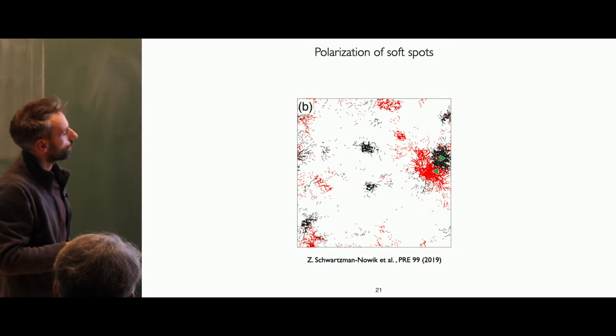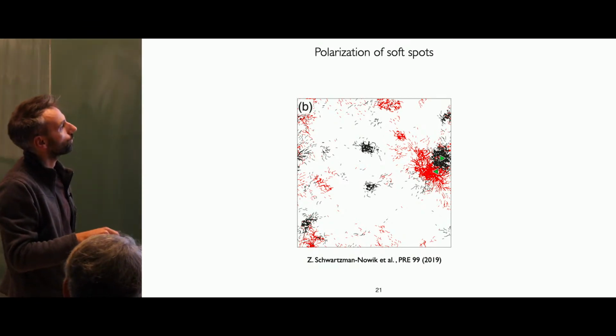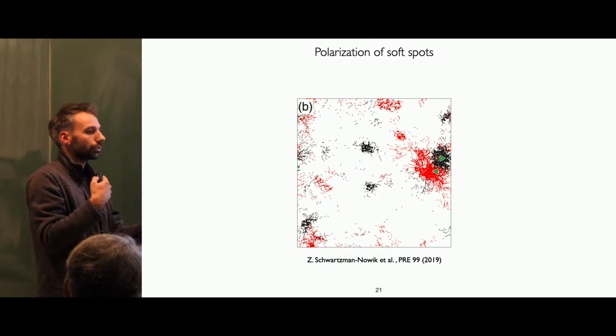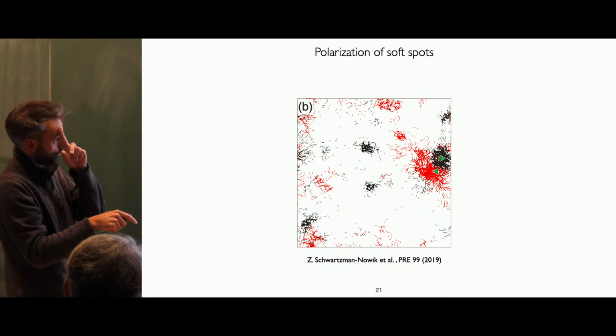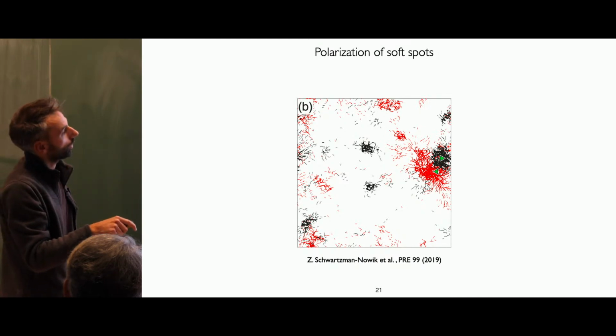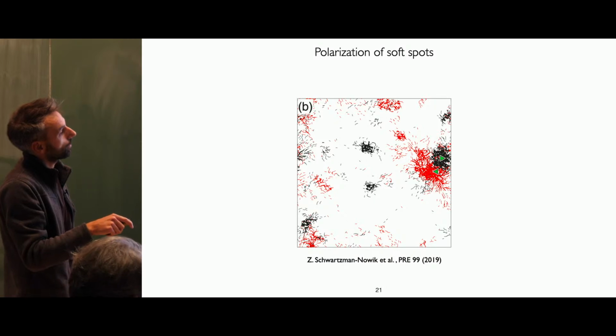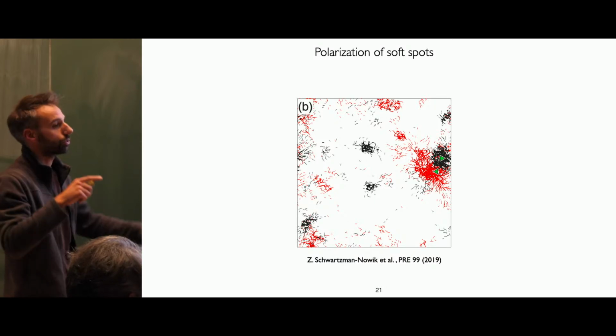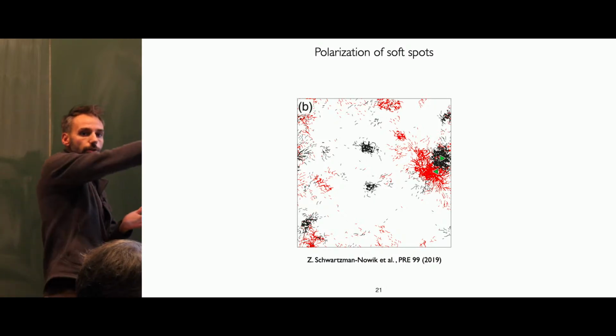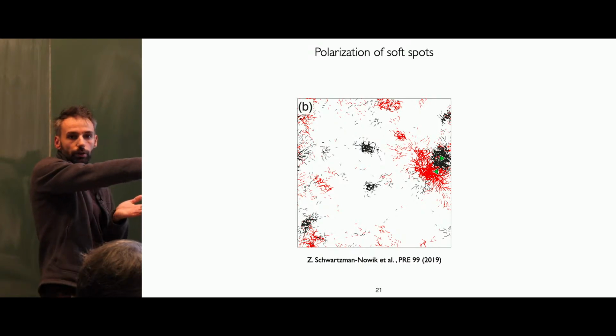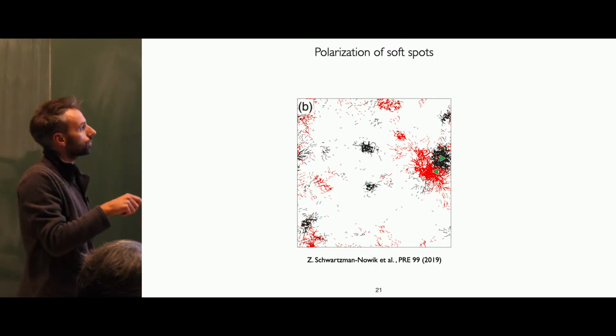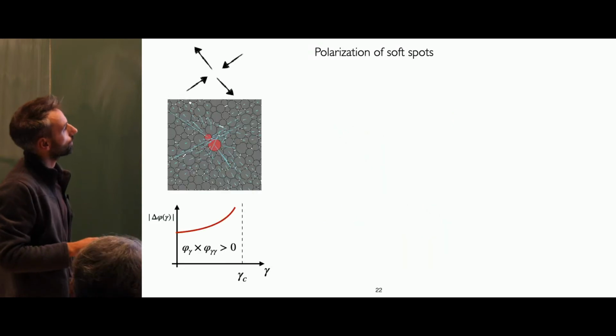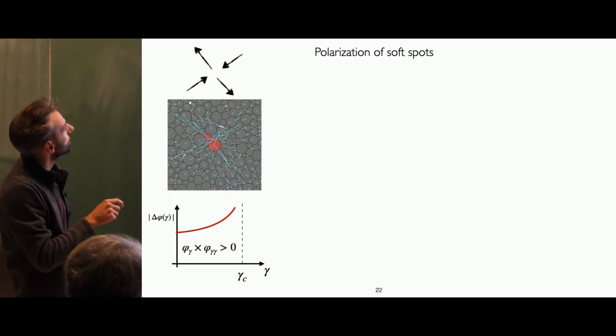And some people have already tried to have such information, so to have a map of soft defects in the glass, but to color them according not only to the deformation, but also the direction of the deformation. And they were able, for some of the soft spots, to detect that this soft spot is going to couple well in simple shear in this direction, and the red one will only couple in the negative direction. So I wanted to do a bit the same thing with my tools.